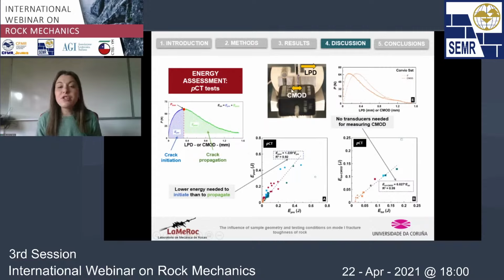And since we also measured the crack mouth opening displacement, we compared the shape of the curves plotting the load against the load point displacement or the crack mouth opening displacement, and computed the area below, the total energy measured in both cases. We observed a very good correlation between these two magnitudes, so that for the PCT there won't be need of using transducers for measuring crack mouth opening displacement as long as we apply this correction factor. And this can be really useful when we are testing small size samples in which we don't have much space to attach the clip gauge.